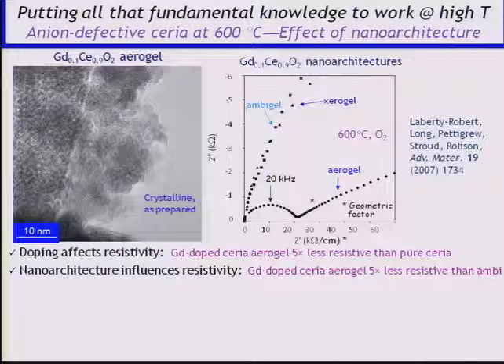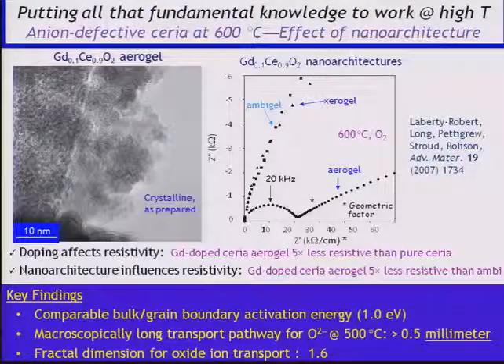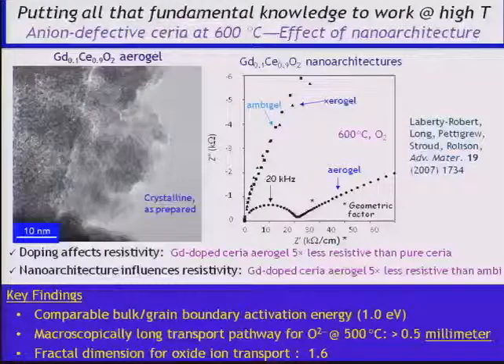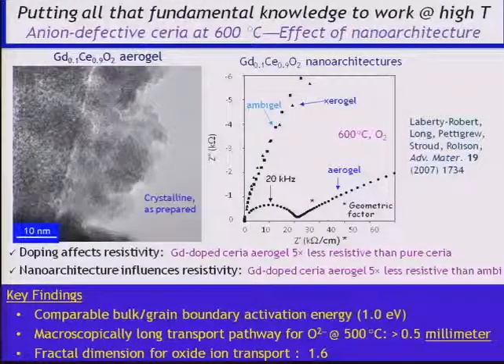And when you looked at the impedance at 600 degrees C in an oxygen atmosphere, we get a Warburg back. So again, we've got a long path for the oxide ions. We could back out the activation energy for transport of oxide ion in the system. That is, in essence, the single crystal value for gadolinium-doped ceria, although this is nobody's idea of a single crystal. Again, the long transport, again, about 1.6 dimensional.